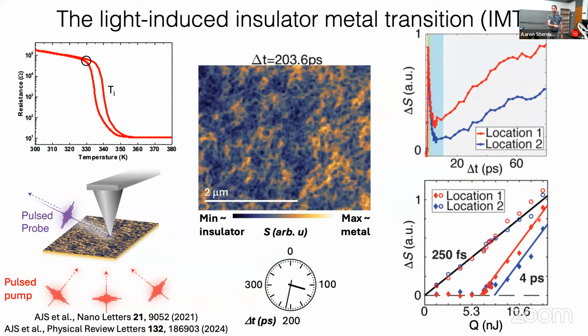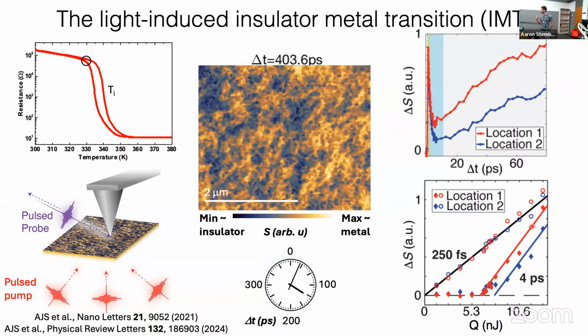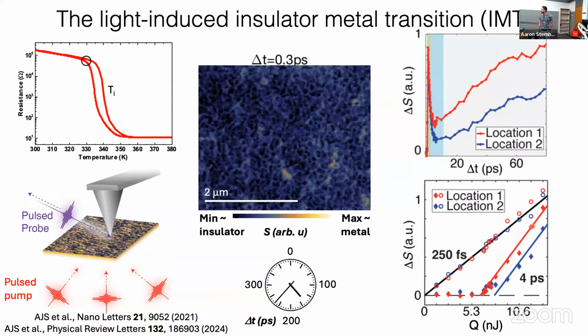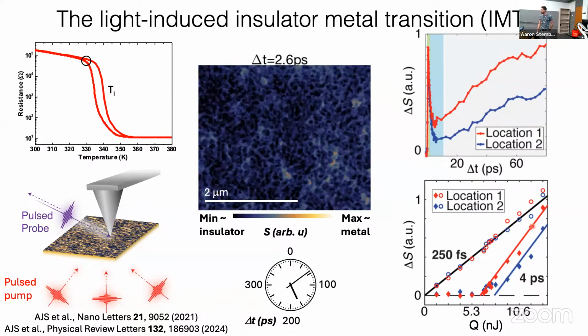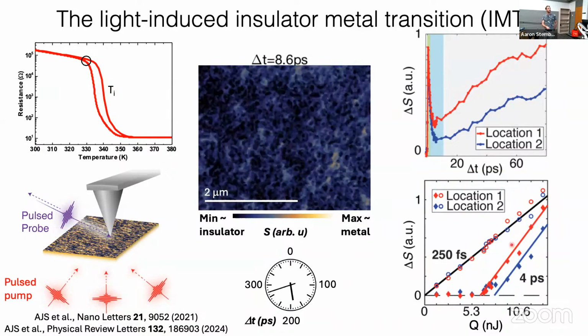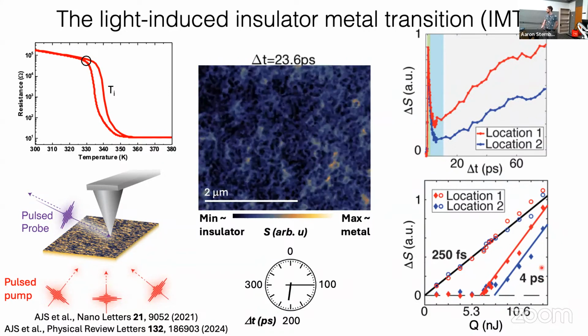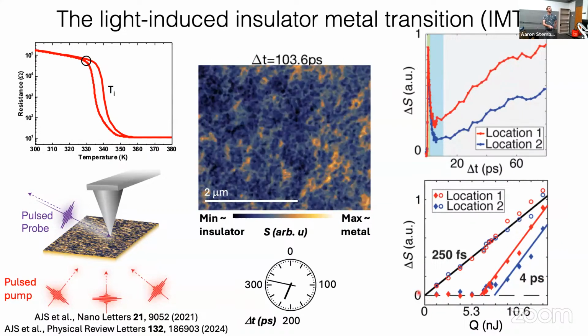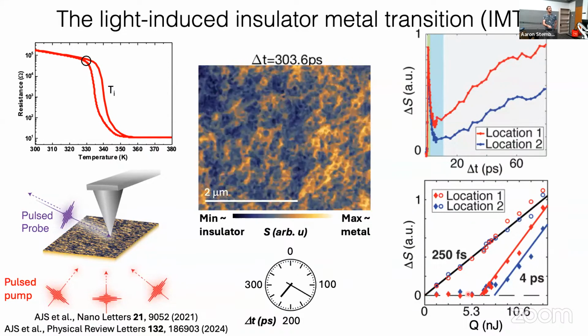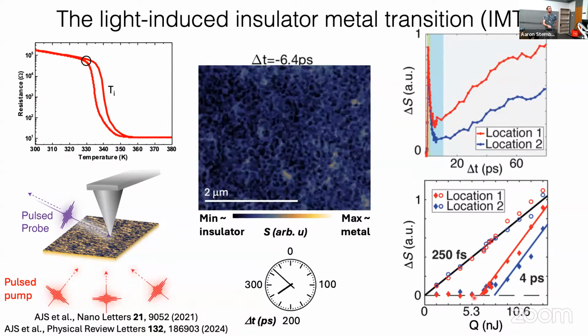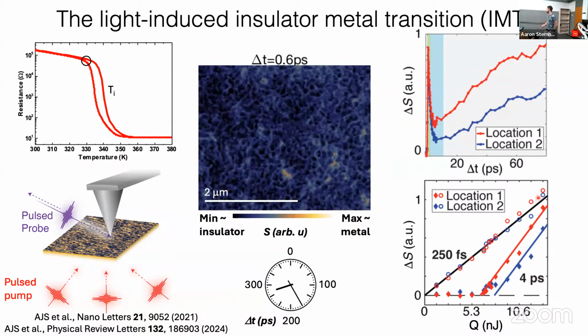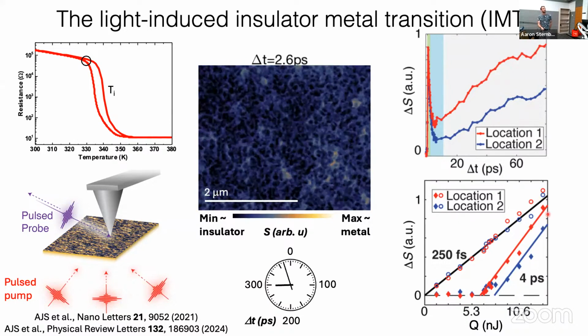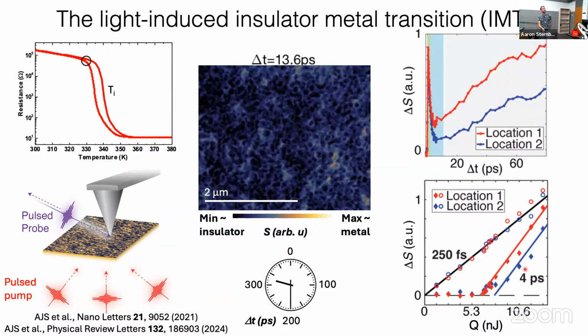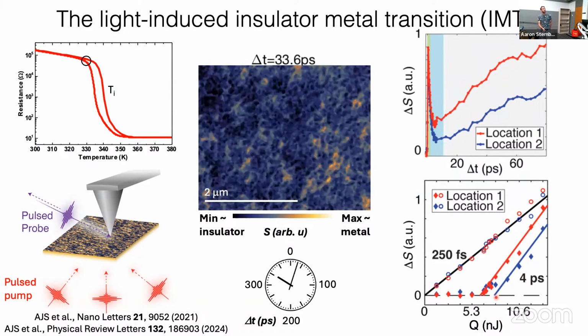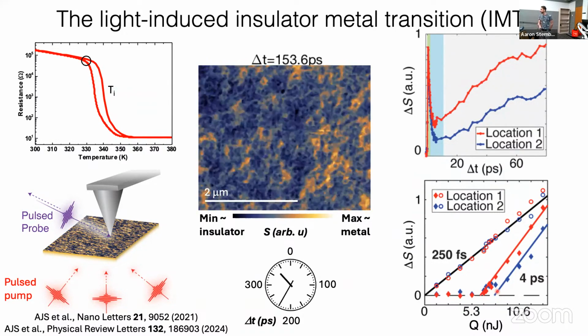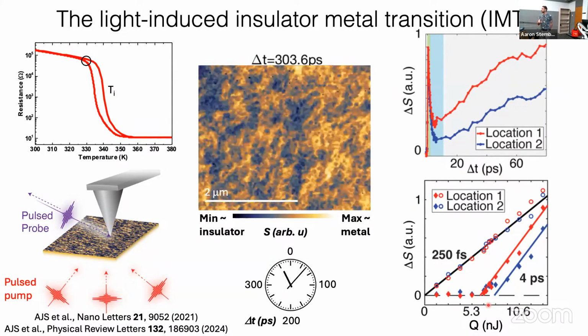fluence threshold. What is fluence? Fluence is essentially the number of pump photons. So how hard are we hitting this material with light? And at a later time delay, 4 picoseconds later, we see a different trend. So as a function of fluence, the system first hardly changes, the scattering amplitude hardly changes, and then rapidly increases above a fluence threshold. And extrapolating from the high fluence data with a linear fit, down to zero change in scattering amplitude, we can extract what's called the fluence threshold.